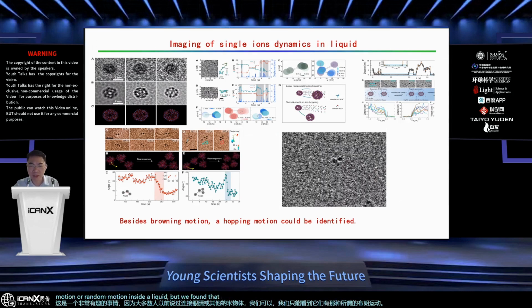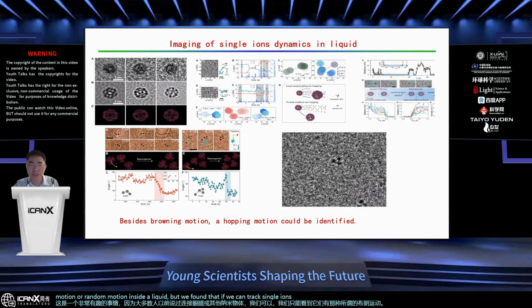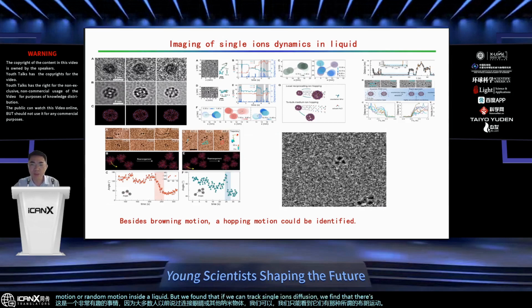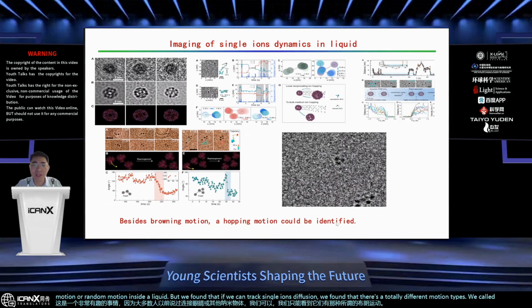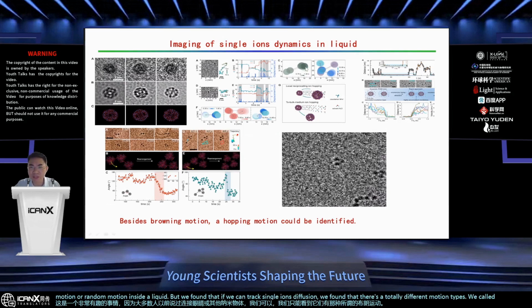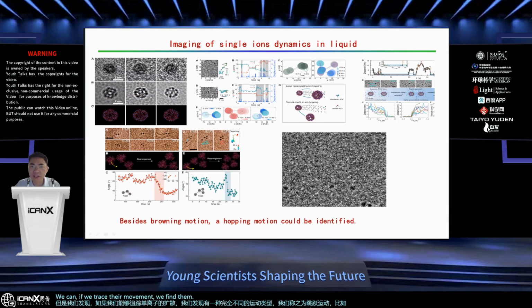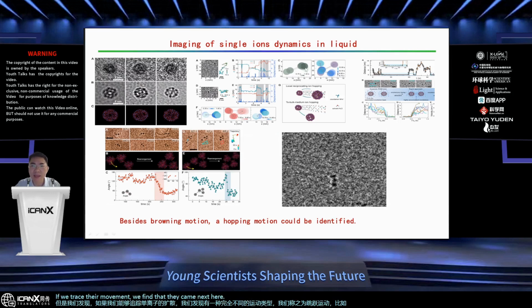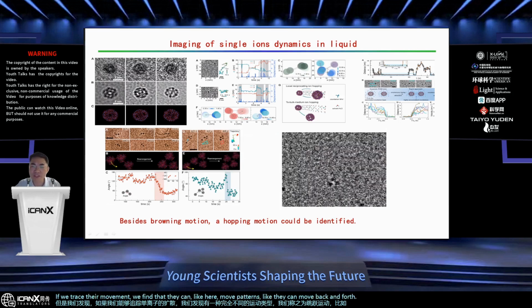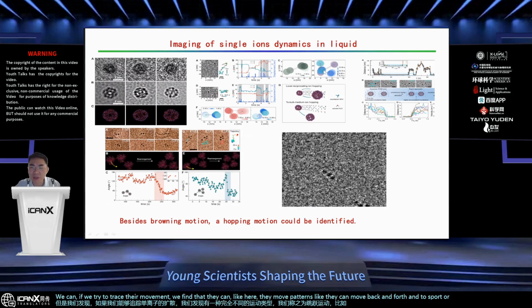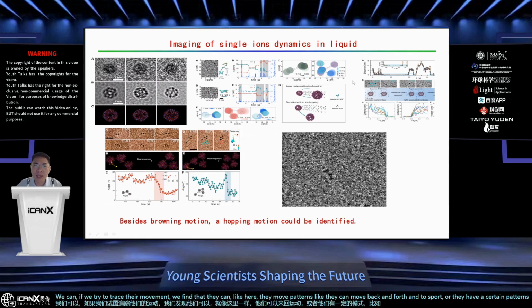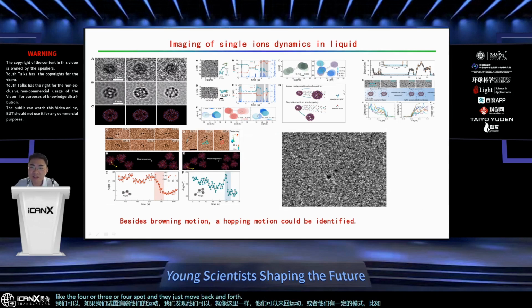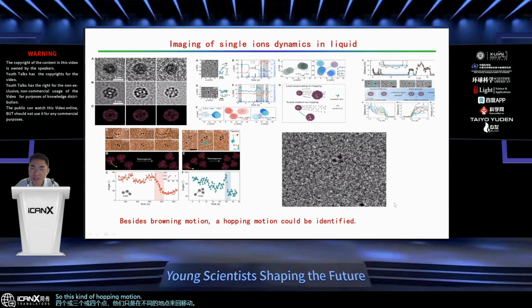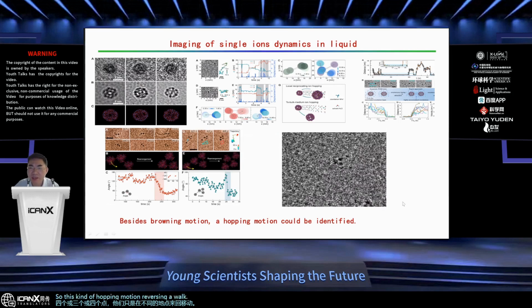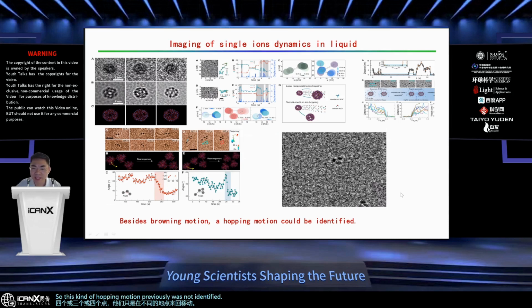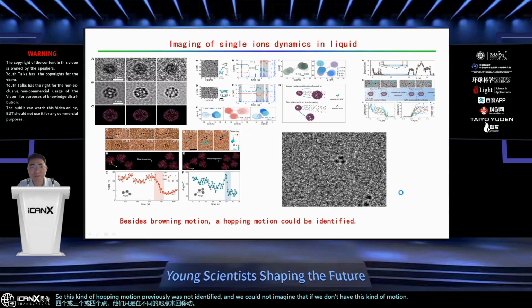But if we can track single ion diffusion, we found a totally different motion type. We call it hopping motion, like the hopping motion over here. If we trace their movement, we found they can move back and forth between 2 spots, or follow certain patterns like 3 or 4 spots, just moving back and forth between different sites. This kind of hopping motion was not identified previously, and we could not have imagined it if we didn't have this kind of in situ observation.